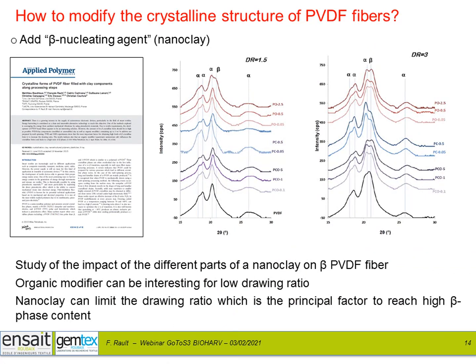In the Tenerife project, we have notably studied the influence of the addition of clays and its different elements, trying to dissociate the impact of the inorganic part and the organic modifier. The main conclusions are that the organic modifier can be interesting for low drawing ratio. However, a too high content of nanoclay limits the drawing ratio, which is the principal factor to reach high beta phase content.